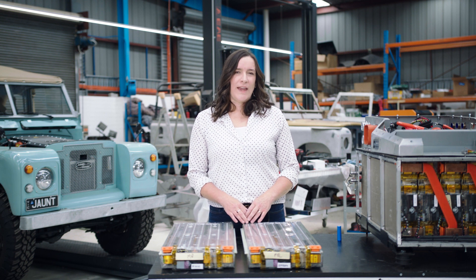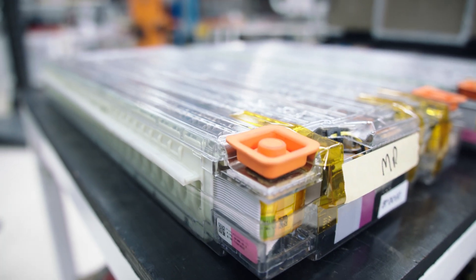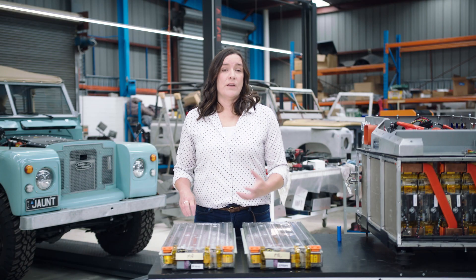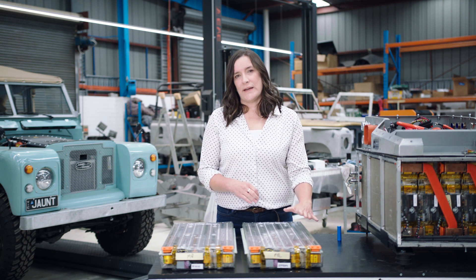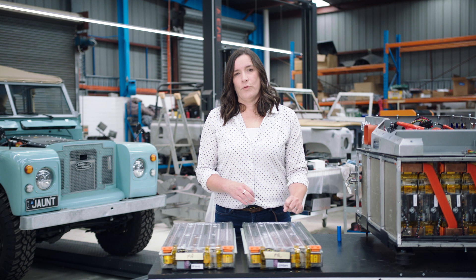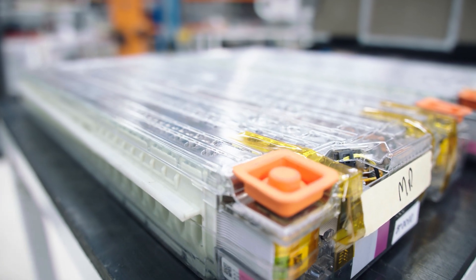In 10% of the cases we studied there was a re-ignition event. In six cases a tow truck was damaged and in two cases a tow truck driver was injured. If we go back to our pretend electric vehicle traction battery — the module over here has gone into thermal runaway, ignited and been suppressed, and we're getting ready to remove it from the scene. But what we can't know is that this module over here had a cell that was also impacted in the initial collision and has now short-circuited and is going into thermal runaway. This causes a re-ignition event — not re-ignition of the original cells, there's nothing left to burn there — it's a re-ignition of the battery pack overall.